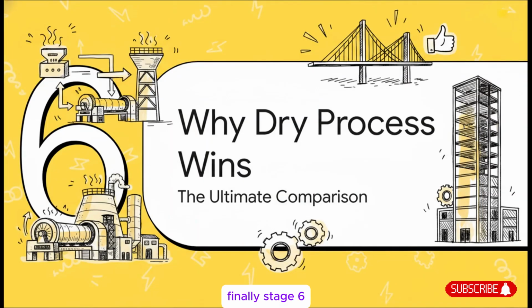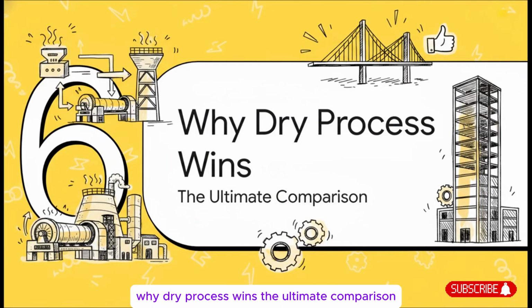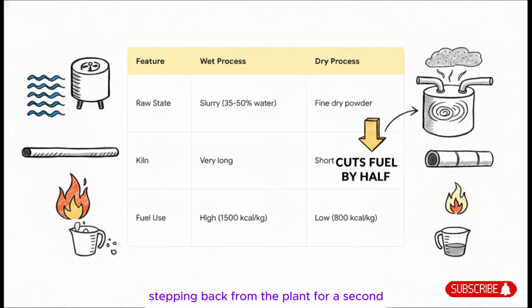Finally, Stage 6, why dry process wins, the ultimate comparison. Stepping back from the plant for a second, let's lock in why civil engineering overwhelmingly relies on this exact method today. This comparison says it all. By dealing with a fine dry powder instead of a slurry loaded with up to 50% water, the dry process allows for significantly shorter kiln structures.